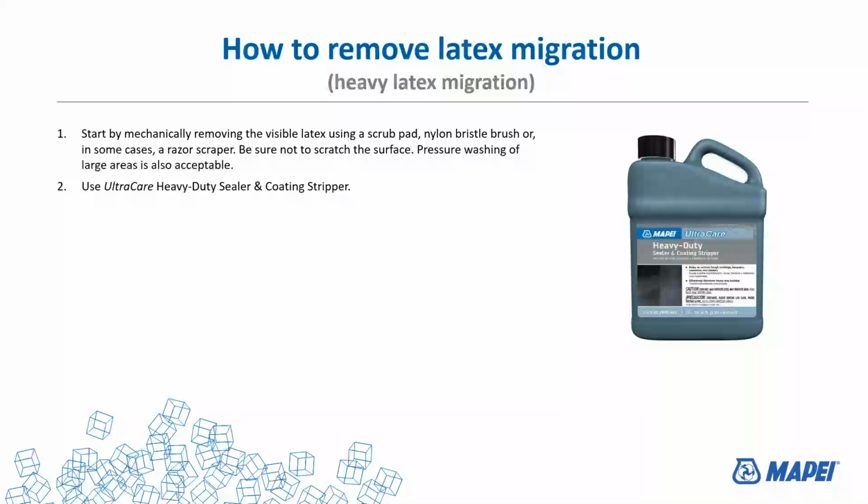This is one place where a heavy nap roller would work quite well to apply it, because you don't want to put it on pretty, you just want to put it on abundantly so it doesn't dry quickly. And it's not a fast drying product. Let's let it stand for 10 to 20 and keep it wet. You can either add more stripper to keep it wet, or just mist it with clean water in a spray bottle, and that'll keep it wet.